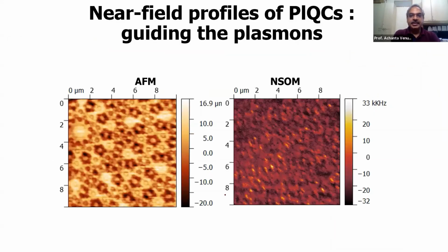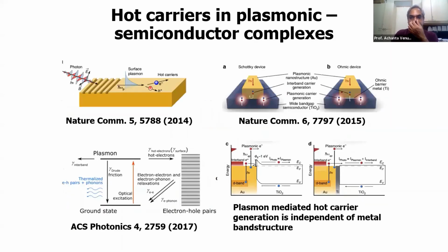These structures have very unique near field patterns. For example, you see this pattern here, the plasmon mode is propagating like a topological pathway, propagating along this direction. So these are interesting for hot carrier studies. When the plasmon is excited, plasmons have a short lifetime, of the order of a picosecond at the most, because they scatter with the sea of free electrons inside the metal. But then what happens to them? These are high energetic, so they are going to generate hot electrons, or high energy electrons, with energies larger than the Fermi energy, for example.